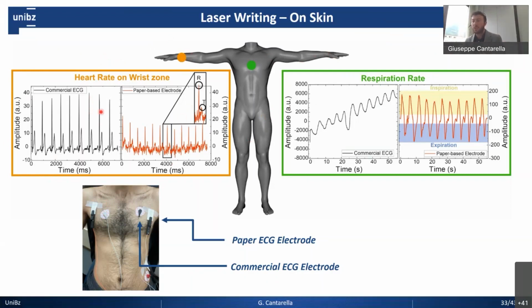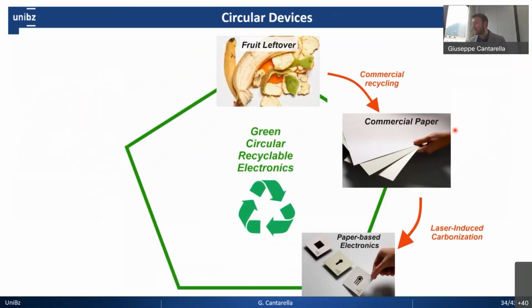And you see that clearly with the commercial ECG we get a higher amplitude, but with the paper one we could easily identify the R and T peak and also the heartbeat. So the heart rhythm is perfectly equal to the one that we can get with commercial electrodes. Even for the respiration, we monitored whether with this paper we could, for example, monitor the inspiration and expiration. And as you can see here, all the positive amplitude represented an inspiration, and all the negative amplitude represented expiration. And this was based on the change of the impedance of our lungs, so considering the presence or not of air inside.